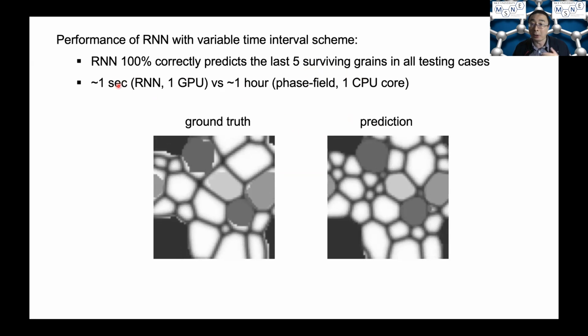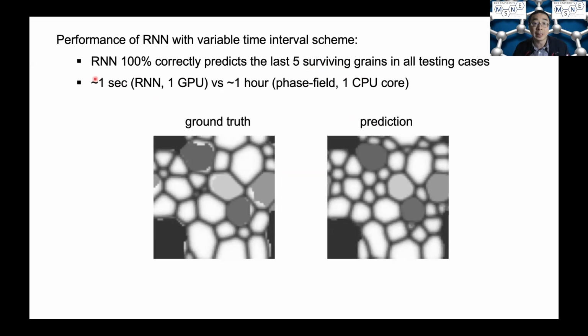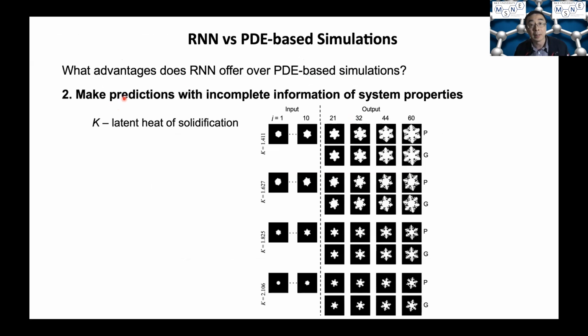And in this case, by using this variable time interval, we can further accelerate the machine learning. It can achieve more than 3,000-fold acceleration compared to the phase-field simulation. And another important benefit, I think, with the machine learning prediction is that it's able to make predictions on microstructure evolution even when the properties of the system are not completely known. Right? So when we use PDE solver simulation to simulate microstructure evolution, we need to know all the parameters in the materials, which are captured by the equations. Otherwise, we cannot run the simulations.